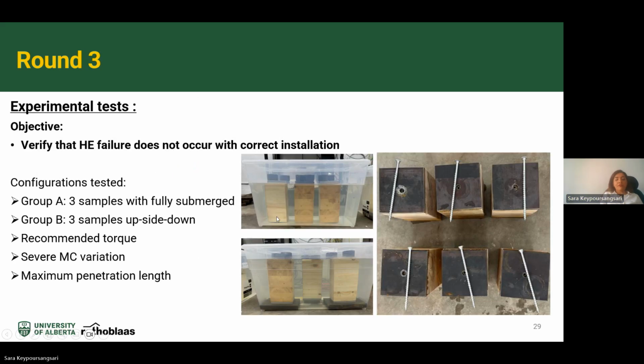Finally, in round 3 of this test, we want to verify that hydrogen embrittlement failure does not occur with correct installation. In this round of the test, we divided our samples again into two different groups. In group A, we fully submerged our sample into the water. And in group B, we put our samples upside down into the water. Our target was finding whether we could find any failure under the severe moisture content or not.